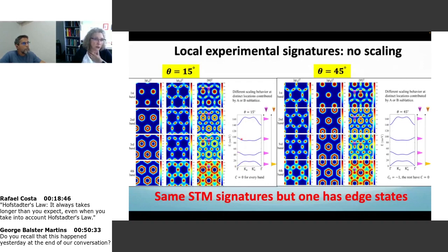These are the bands. I am only plotting here the conduction band for an orientation of 15 degrees. I can put an STM tip here, and I can put an STM tip here. These are the places where I am going to get a signal. As I said, at 15 degrees I will have a 0 Landau level, which will be part of a particle in a box spectrum, but a particle in a very deep box, in a very deep potential well. So I will pick up the signature with my yellow tip of a Landau level there, and the next level will be way above this, 160 millielectron volts, because it will be separated by particle in a box type of physics. These guys will not have much contribution of the 0 mode.